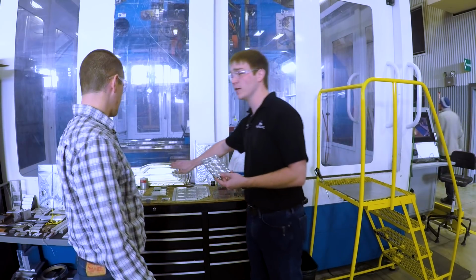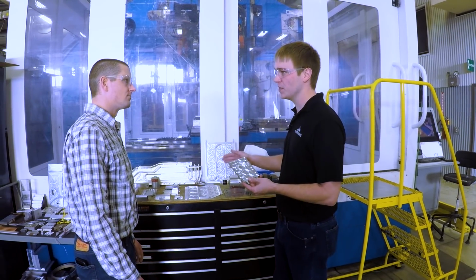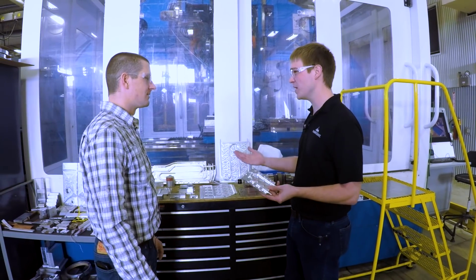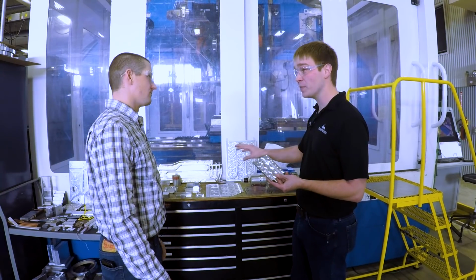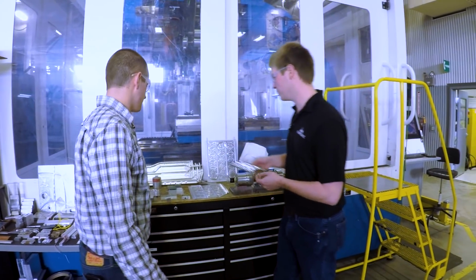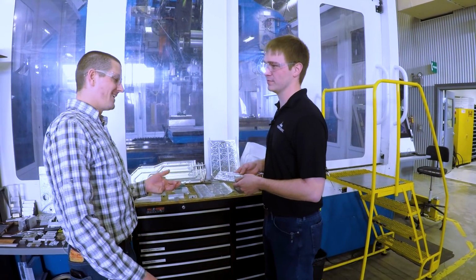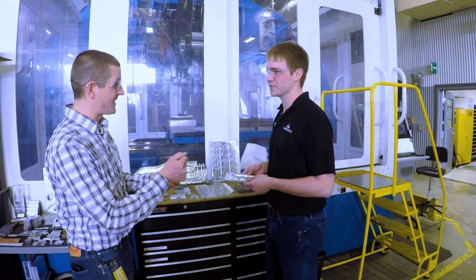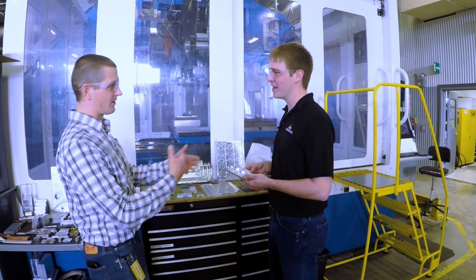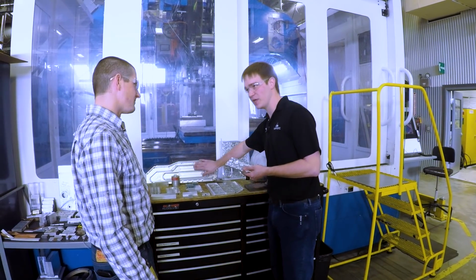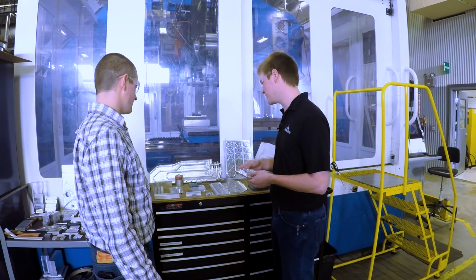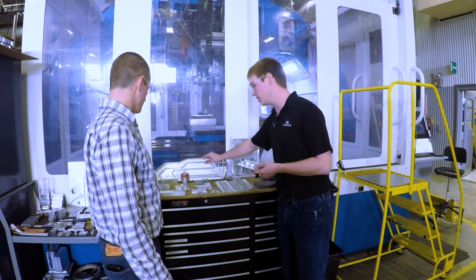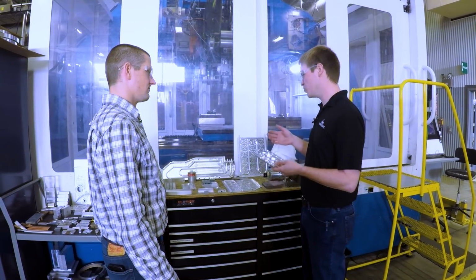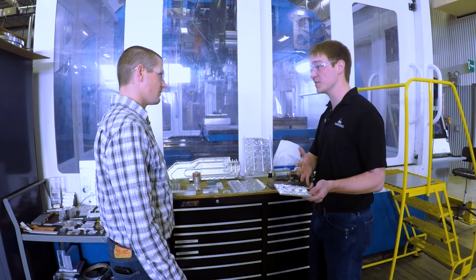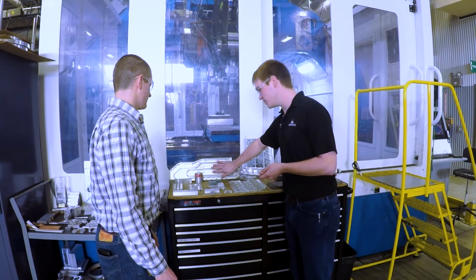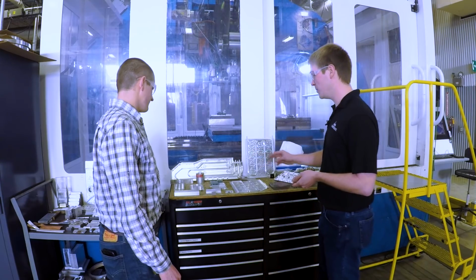The current manufacturing method for a panel like this would really be just bolting and epoxying a bent tube onto a plate, which, when you think about it, has lots of moving pieces, is much more complicated, and has a lot of opportunities for failure, as well as the weight savings. I'm thinking back to when I was a kid and I would try to overclock computer chips by putting thermal paste on there and a bigger heat sink. I've got to think that this being monolithic is a better transfer of heat. Exactly. If you look at just the sheer thermal conductivity increase when you get rid of the epoxy and you have different wall combinations, by going to monolithic 6061 aluminum in the T6 condition, we're able to get good mechanical properties and good thermal properties with massive weight savings. By getting rid of that epoxy and all the other pieces, we achieved a 30% weight reduction compared to the current manufacturing method, in a significantly shorter lead time.